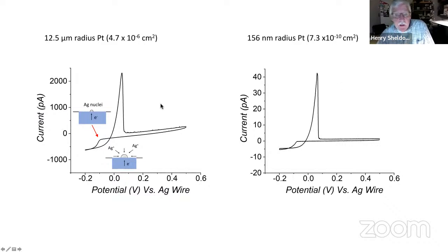All right, the difference in the areas of these two electrodes is a factor of 10,000. This electrode is 10,000 times smaller than this electrode. When you do the experiment on this electrode, you get many nuclei, many particles on the surface. And when you did the experiment with this tiny platinum nanoelectrode, you only get one particle, one nucleus, one particle. And I'll show you how we figured this out.